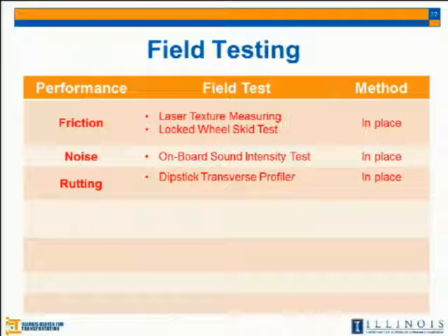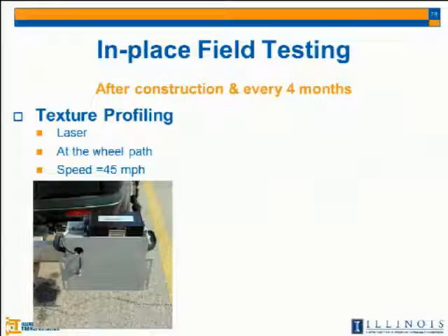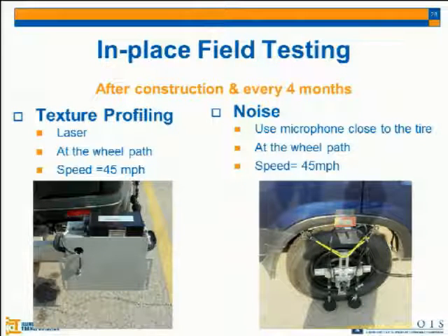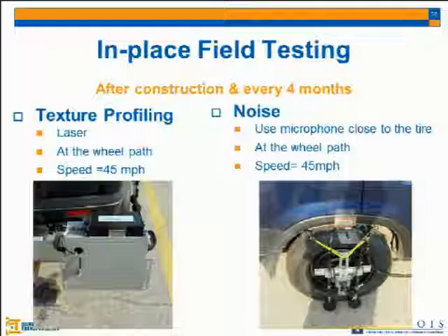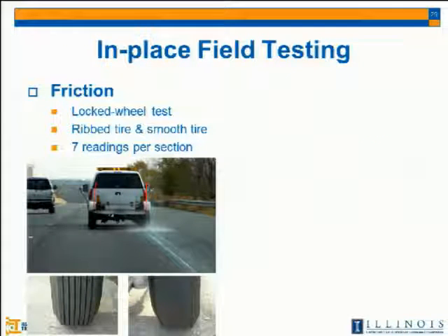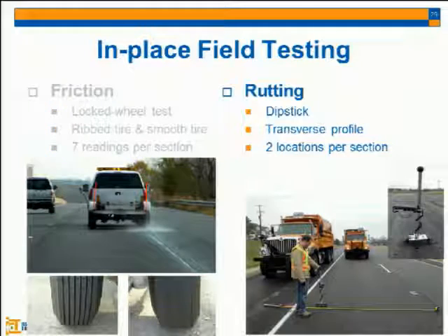We did field testing for friction, noise, and rutting. We did the texture profiling using a laser at a speed of 45 miles per hour, after construction and every 4 months after construction. We did the noise test using a microphone close to the tire to detect the sound intensity between the tire and the pavement surface. We also did the friction test using the locked wheel friction test device with 2 different tires, ribbed tire and smooth tire. And we also did measurements in the field under traffic control using a dipstick.